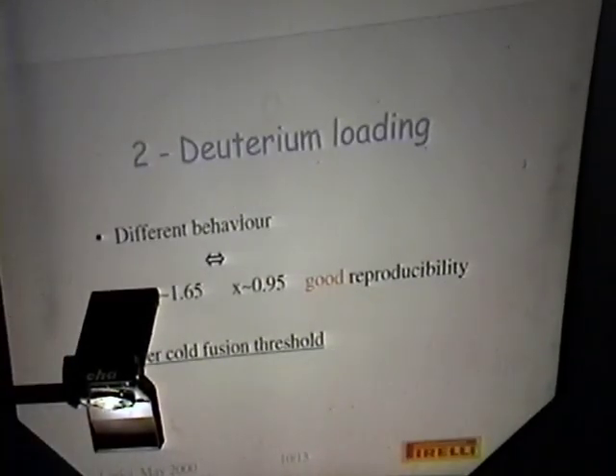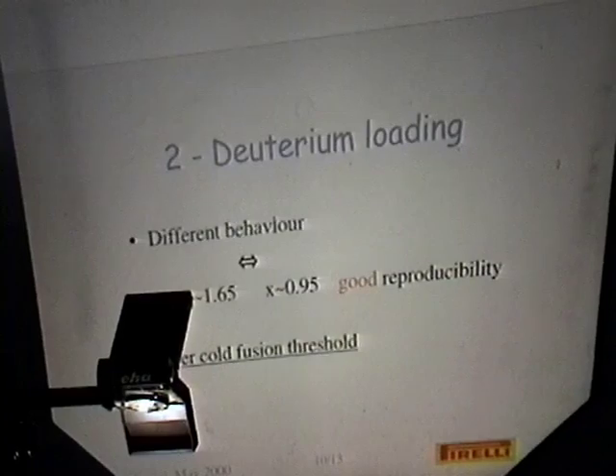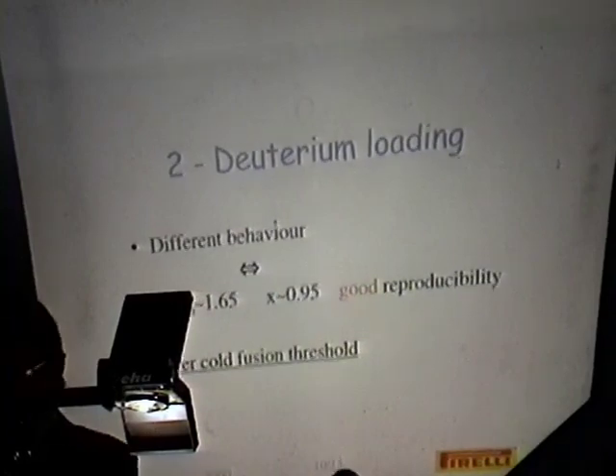Deuterium loading. I write here different behavior in the sense that it is not straightforward to pass from hydrogen to deuterium. In particular, when we use the mercury, there is behavior that could be quite different. In a lot of cases, we obtain that adding a lot of mercury in the solution of a highly loaded deuterium wire, the wire deloads. We don't know why. For hydrogen, this doesn't happen.